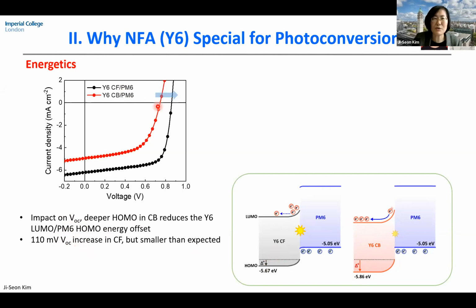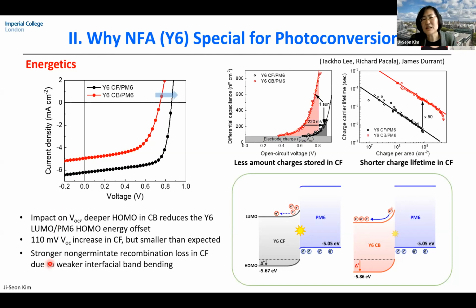However, compared to the energetics, where we measure more than 200 meV, we only observe around 110 meV open circuit voltage change. And it turns out that in the CF phase-oriented molecular structure, there is much less amount of charge stored, and these charges live much longer. And these things can be understood when we consider how this electrostatic potential disappears at the interface with the PM6. Because of less electrostatic potential pulling of the HOMO in the CF case, you have less interfacial band bending. So even though you generate a lot of charge carriers, they will recombine much more easily. So much less charge is stored, and they live shorter compared to the edge-on CB devices. So we can understand how this energetics influences photovoltaic device performance.